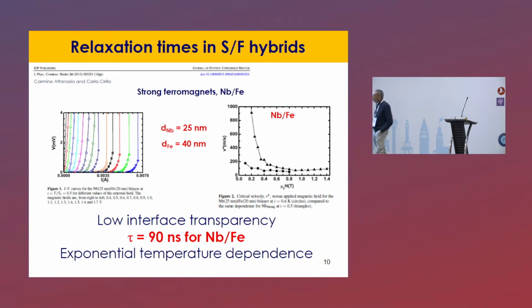So this is the beginning. We started, let's say, 15 years ago, and we started to measure these IV characteristics, this sudden jump in the IV curves, of niobium, which is a material that we know very well, and we asked ourselves what is going to happen if we put a ferromagnet on top of the superconductor. We started with the strongest ferromagnet, iron, and actually nothing happened. So we measured a lot of samples, a lot of bilayers, niobium iron. Here is 40 nanometers of iron, 25 nanometers of niobium, but we changed a lot of thicknesses, a lot of combinations. We always ended up with the same critical velocity.